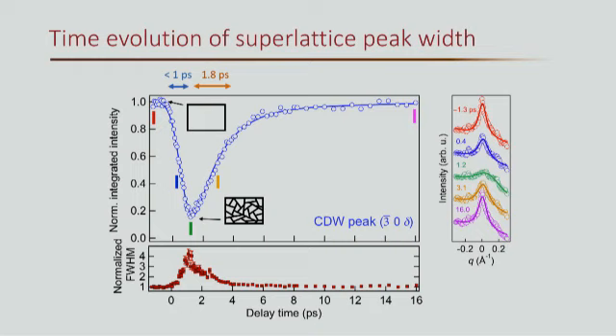Of course, this is not the best picture, because it's really not a static domain sitting there. They will be fluctuating all the time, but I try my best. So the idea here is that the suppression of the intensity is accompanied by the formation of these small puddles of fluctuating charge density wave. You can also look at this graph and see that it doesn't really get suppressed all the way to 0. There's still some residual intensity remaining.